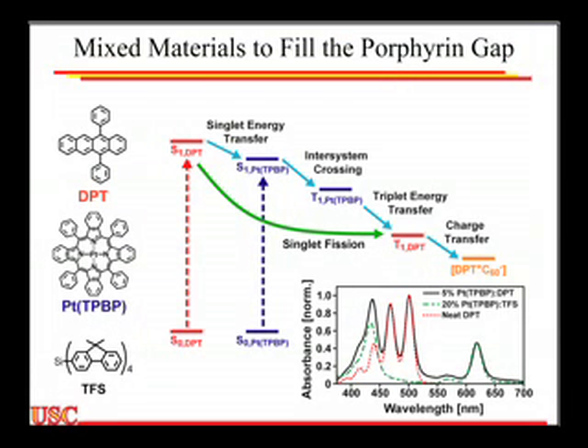And so the key is that, remember that the approach here is that we're going to be hopefully doing singlet fission on this tetracene molecule, although we have no idea whether DPT is going to do it or not, because it's only been demonstrated in crystalline tetracene, and DPT is amorphous. And so the question then is, if we pump this, how efficiently can we transfer energy from my sensitizer to my singlet fission material? Because this is the part that's absorbing, if you like, the red and yellow light, and this is what's absorbing the green and blue light in the sort of picture that I showed you here. So imagine that the porphyrin is my model for absorbing red, and the DPT is my model for absorbing green.